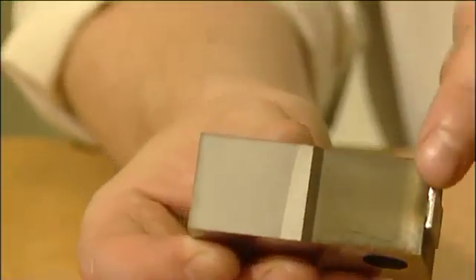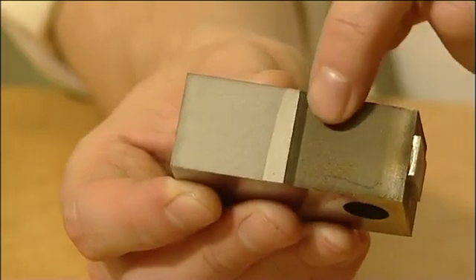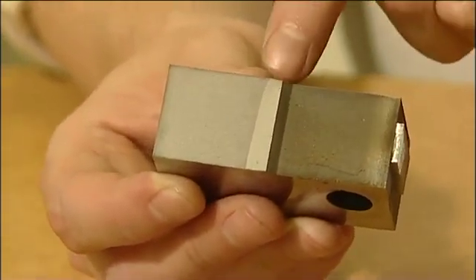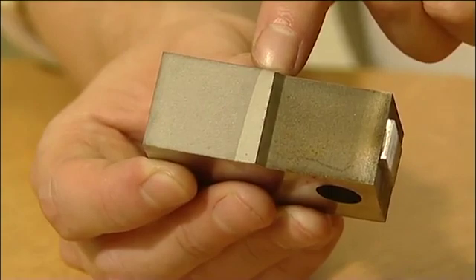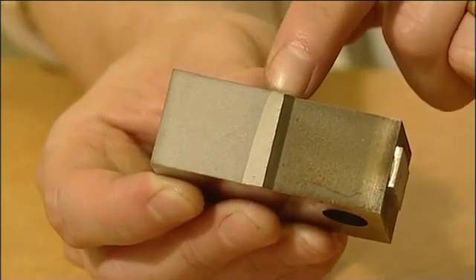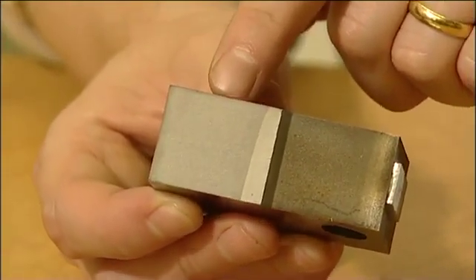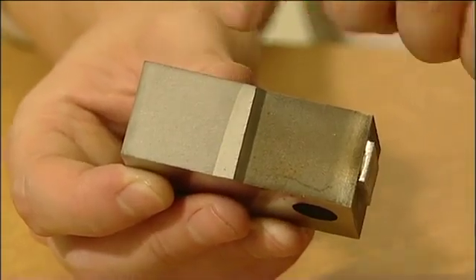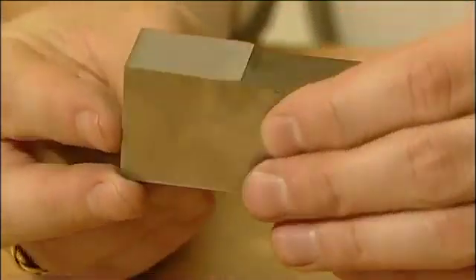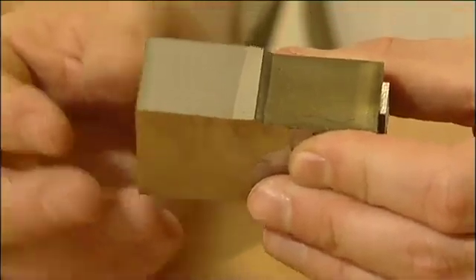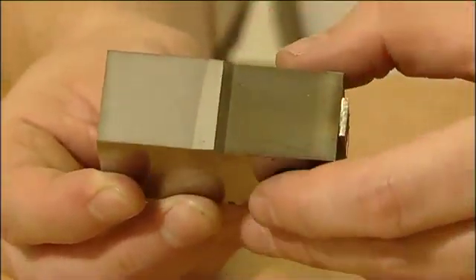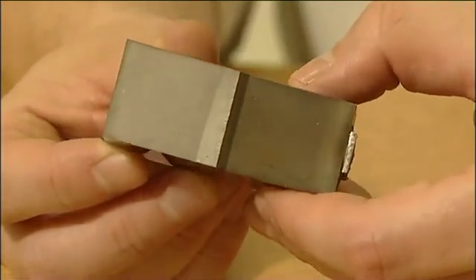If we look at one that's previously been fractured, so this is half of one of the samples you've just seen, what you can see here is the inside of the pre-machined notch. This region here is the fatigue crack that was grown from the base of that notch, and then here we have the final fractured region. You can see that it's very flat, showing that it's a brittle fracture. There's no evidence of any shear lips at the edges of the sample, which would be associated with a ductile failure.